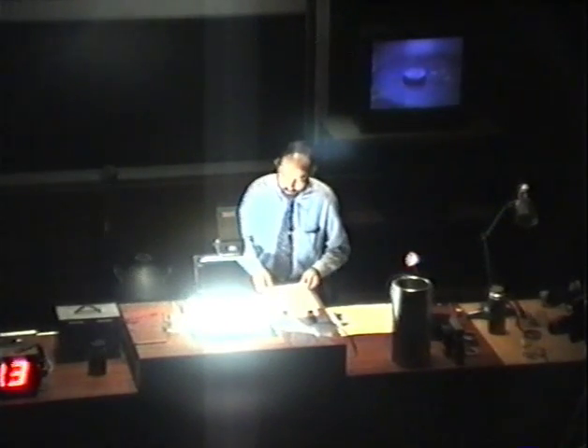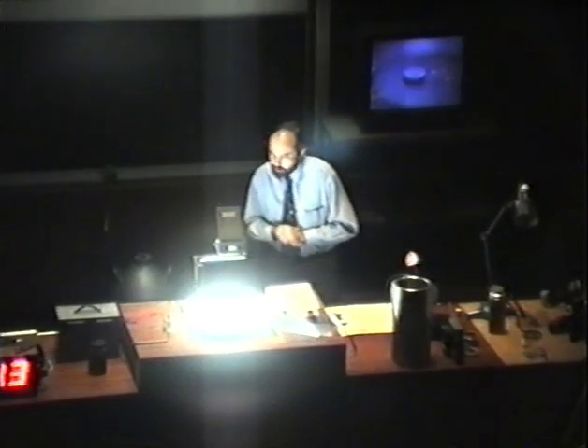But of course, as I said before, the contamination is a problem. If you aren't careful to start with very pure material, your results can be perturbed, maybe not reproducible, because the trace impurities can interfere quite significantly. So what was done, instead of using platinum or gold, they adopted mercury, because mercury you can distill and distill and distill in order to purify, and you can make mercury very much more pure than you can make lead, platinum or gold. And so the big day came.